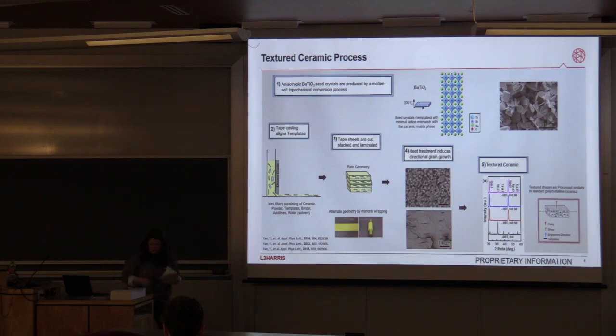What we do is we actually then take this and we cut and stack it. And don't worry if it rips or anything. So for the next step, we cut and we stack this so that we can align these seeds in this direction here. So going up, we have alignment going this way. Other than stacking it, we can also cut it and wrap it around a mandrel. This gives us another geometry that we can't do with single crystal. If you were to do this with single crystal, you can't grow it in this direction. So it actually opens up things that single crystal cannot.